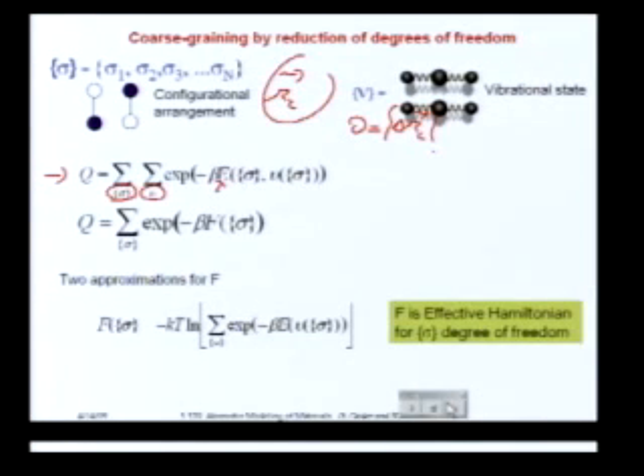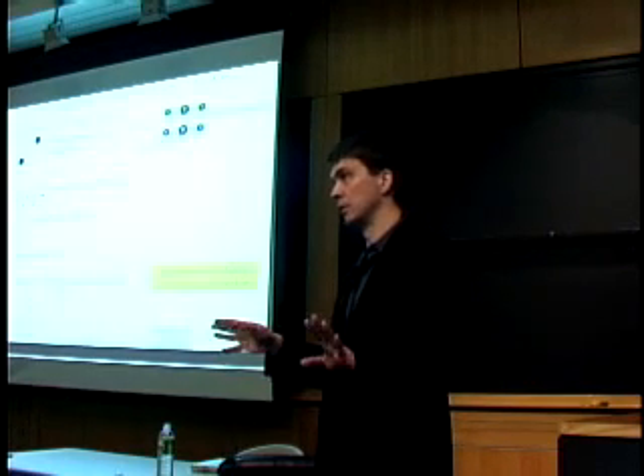Okay? Now what I'm going to do is essentially assume I can do this integration, and we'll talk in a second about how you can do that. So I'm only going to do the sum over the displacement, but for a given configurational state. So what does that practically mean? That means that I'm integrating the phase space of a fixed topology, but allowing the atoms to sort of vibrate around their average positions. That's essentially what I'm doing. So essentially I'm capturing in that integral the vibrational free energy component for a given configuration.